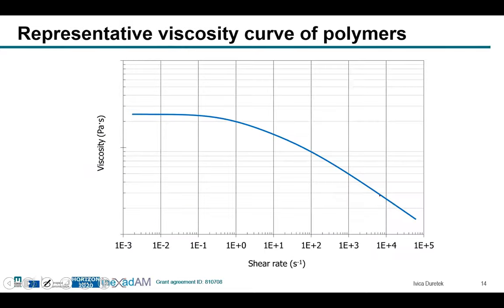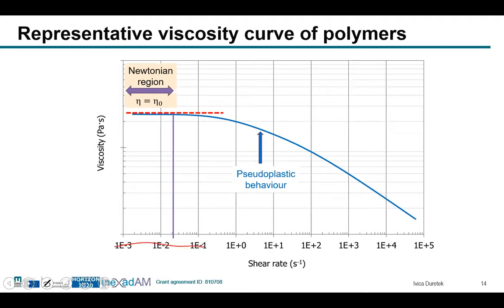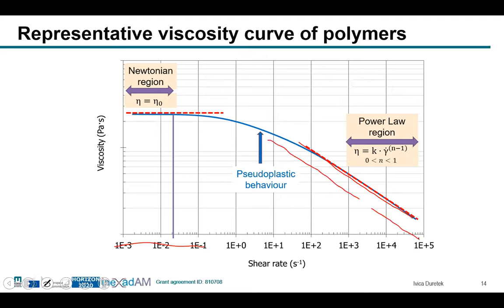On this slide, you can see the typical viscosity curve of polymers. In the range of low shear rates, we have the so-called Newtonian region. It means that the viscosity is independent of the shear rate. In the range of higher shear rates, we have the so-called power law region, and between is a transition region. All polymers show so-called pseudoplastic behavior. That means with increasing shear rate, the viscosity decreases.